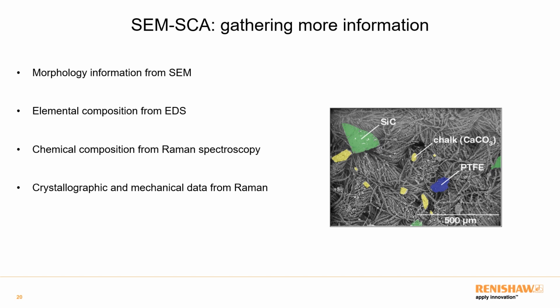The same to some point is true with the chalk. In this case it's calcite, calcium carbonate, and we would be able to get the elemental information from EDS, but we wouldn't be able to identify which polytype of calcium carbonate it is, so we wouldn't know if it's, for instance, calcite or aragonite. However, Raman is able to give us that crystallographic information, so we're able to get a positive identification.